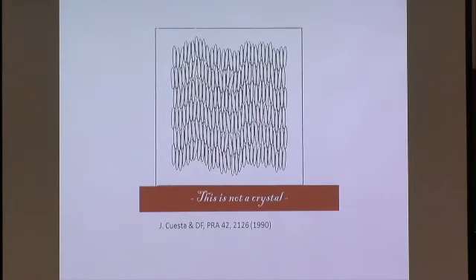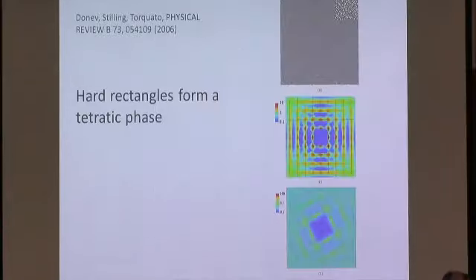I would be a bit hesitant to call this a nematic phase, although actually probably on sufficiently long length scales, this is what you would call a nematic phase. But bond order for non-spherical particles you see everywhere as soon as you go to non-spherical particles in 2 dimensions. Now there's actually another way to make these tetratic phases with 4-fold orientational order, and that's by taking not squares but taking rectangular particles.